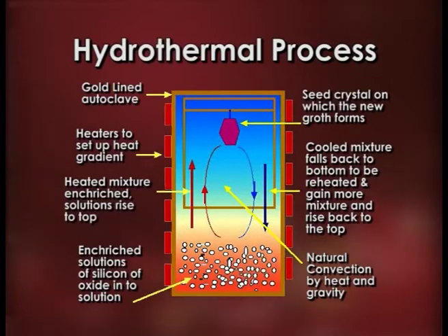By the second method, a hydrothermal process, quartz, opal, beryl, corundum, and fluorite are crystallized from solution under conditions of higher temperature and pressure by dissolving fragments of the mineral and redepositing it as transparent gem quality crystals. In laboratory experiments, most of the important gem minerals have been produced by crystallization from solution. However, only those mentioned above are produced on a commercial scale.